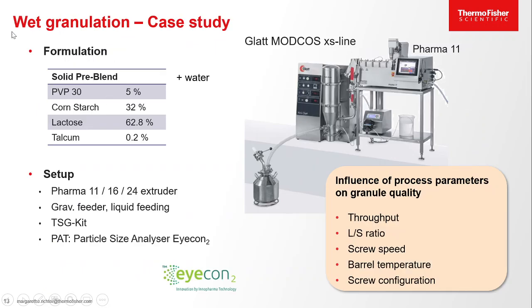Here we have a short case study of a wet granulation process based on mostly a lactose placebo formulation with PVP 30 as a binder and water that is used as a liquid. We checked this on different sizes of extruders, so Pharma 11, 16, and 24, so we could really scale up the process. Gravimetric feeding is used, and we also did some inline measurements of the granules.